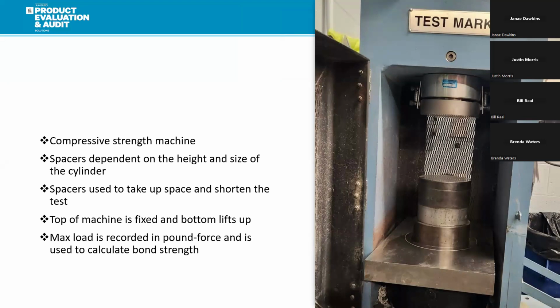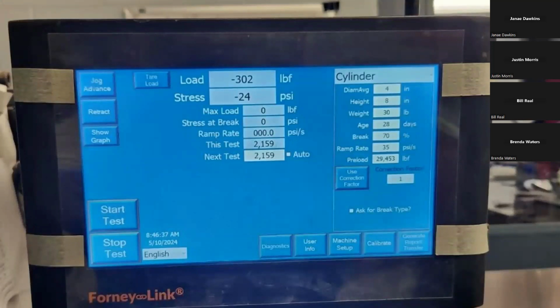If you had that much space in between tests, it would take that long for the equipment to move up to get a result. The top of the machine is what's fixed, and the bottom is what lifts up, and the max load is recorded in pound force, and it's used to calculate your bond strength. And this is just a picture of the computer that you use. You have to put information in, like your diameter of the sample, your height, your weight, the age, as long as how many days you allowed it to cure, the break you're expecting, the ramp as what the bottom plate is coming up to, and then you get your results.